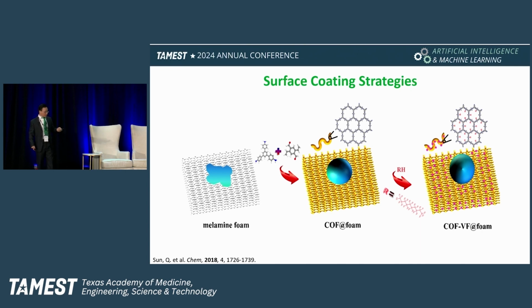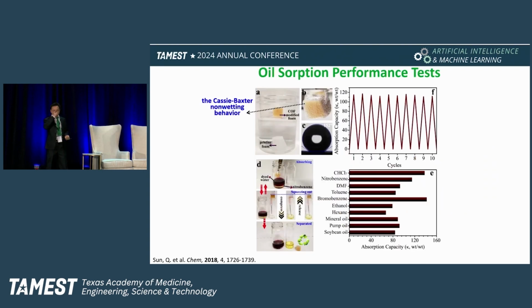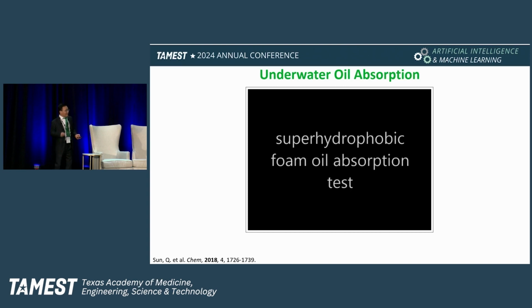We coat it with a little less than 2% of our material, and we make it super hydrophobic. Then we can absorb a lot of organic materials. Nitrobenzene is heavier than water, and 1 gram of our material can absorb over 100 grams. 1 gram of this functionalized melamine foam can absorb 100 times its weight. It's a huge absorption capacity. We also have a video to show.